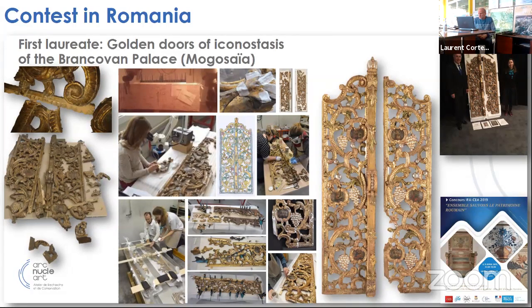After emergency fixing of the polychrome layer, then irradiation, the conservator did condition report studies and a polychromy study that revealed different layers of painting, of gold and silver layer. And initially it was thought that the nuclear consolidation with radio-curable resin could be very convenient. But finally, it was not done, in order to preserve the possibility to reach the different layers if necessary, because after such treatment, which is completely irreversible, there is no possibility to reach the different layers again.